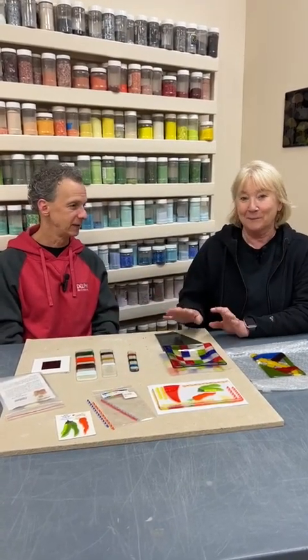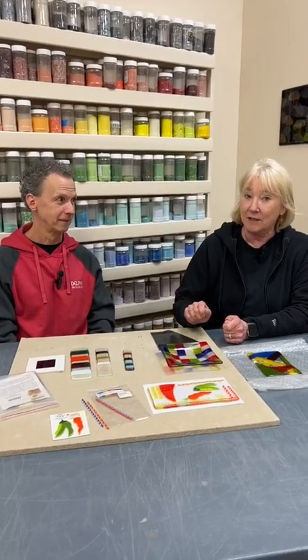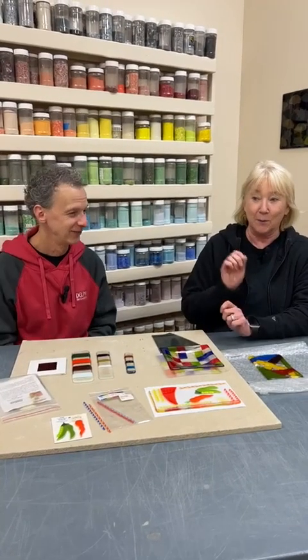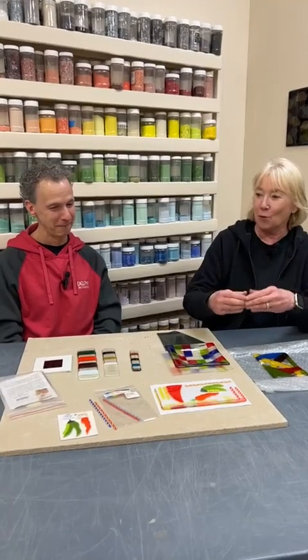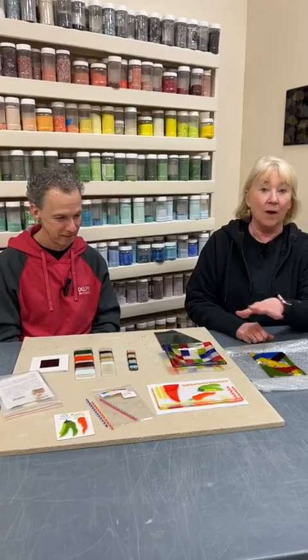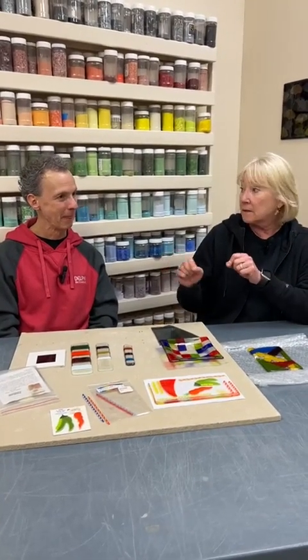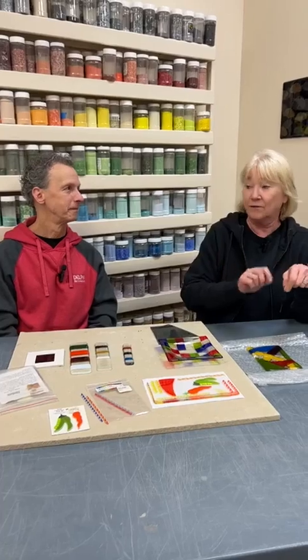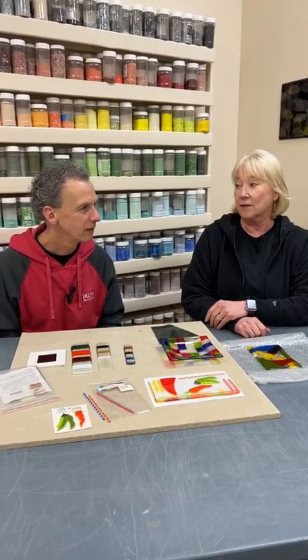That's what I always say in my class. It's not magic, so you have to have a control. There's no little voice that goes, I'm 90, I'm 96. You have to have a control of whichever COE you use, and you know what that is, and then you put your suspect mystery glass and fuse it on top. If it's compatible, there's no stress or little stress.